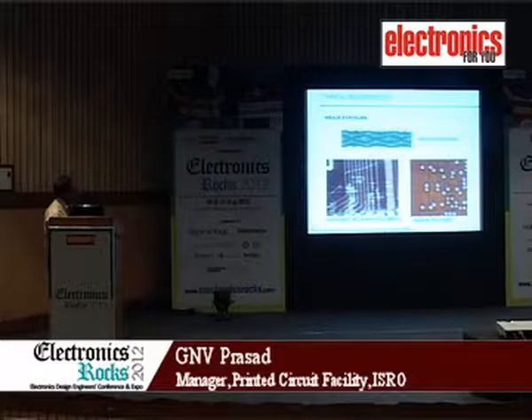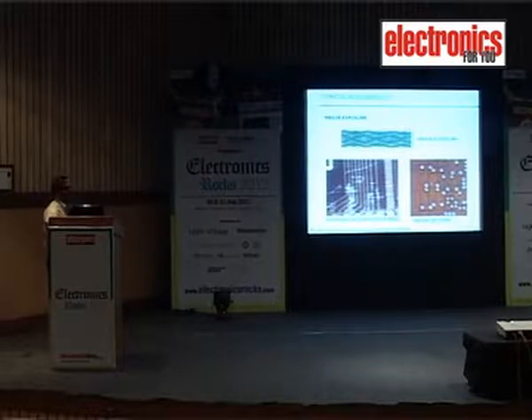Such defects will become porous in this zone. It will become porous and start accumulating contaminations during the soldering or during the assembly process, and these contaminations can further reduce the IR and also reduce the dielectric voltage withstanding capability and finally lead to the failure of the PCB. You can see many such spots. This is mainly due to thermal effects, the weave structure getting disturbed.